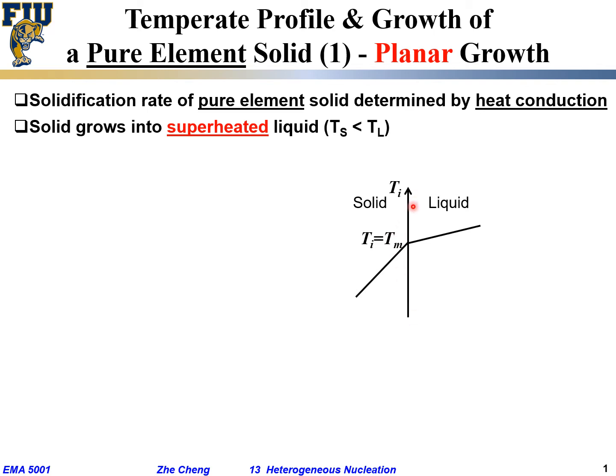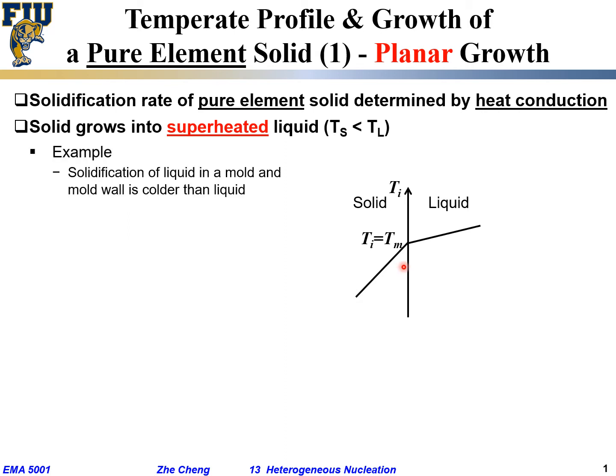Okay, and the vertical axis is for temperature, and as we illustrated here, the liquid temperature is higher than solid temperature. The liquid temperature on the right side is higher than the solid temperature on the left side, which satisfies our so-called superheated condition, which means liquid temperature is higher than solid. Okay, and this scenario happens when we pour hot liquid into a cold mold, and the mold wall is colder than the liquid, and you are extracting heat away from the mold or from the solid side. Okay, and the liquid side is hotter, and the deeper into the liquid, the higher the temperature. The deeper into the solid, the lower the temperature. Okay, this is the scenario.